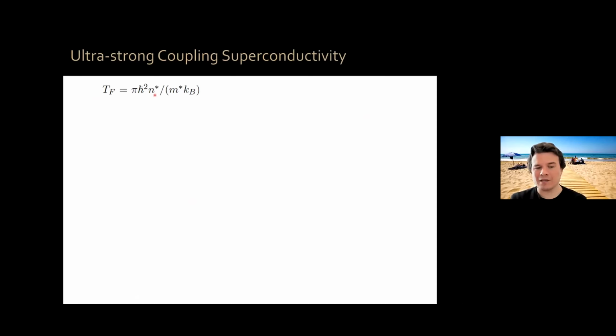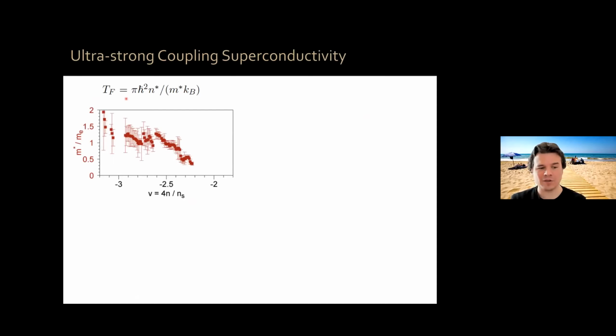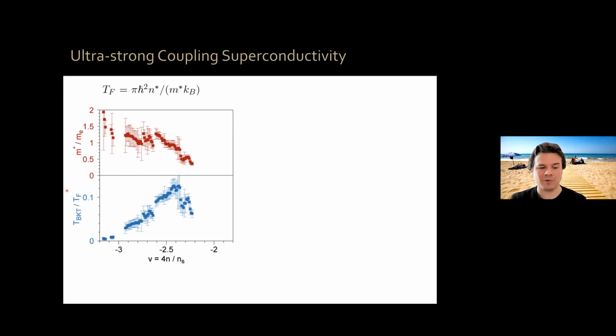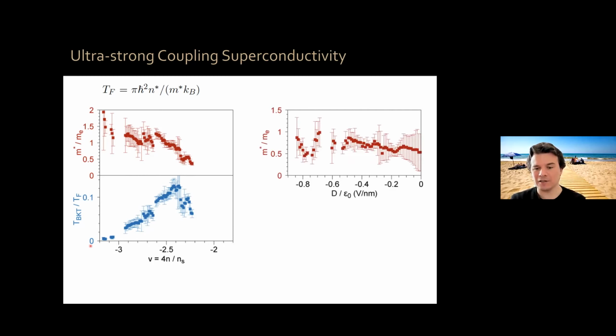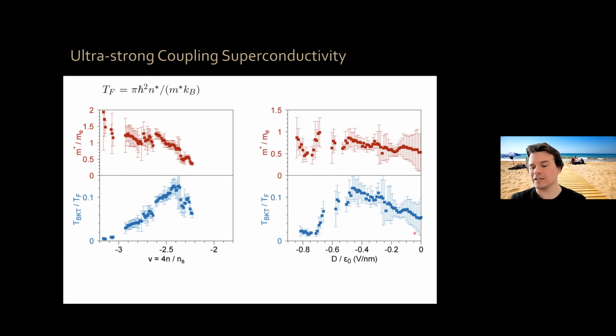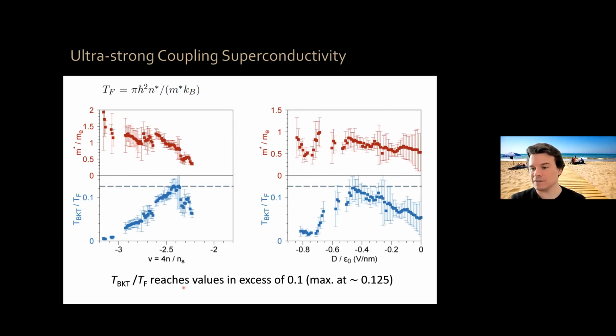So, because we can measure our Fermi temperature and our TBKT, by measuring, for example, the density and the effective mass, we can plot TBKT over TF as a function of density at optimal electric field. We can do the same thing at optimal density as a function of displacement field. And this is 0.125. So TBKT over TF in the system reaches values in excess of 0.1, with the maximum actually at about 0.125. So this system is close to the BEC-BCS crossover.